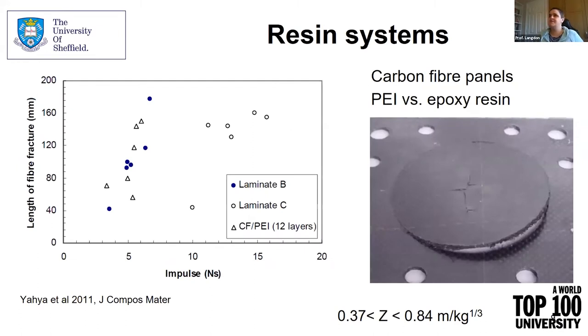So now, instead of the carbon fiber PEI panels that we saw in the last slide, we're now going to compare them to carbon fiber epoxy systems of equivalent mass. If you have a look at the graph on your screen, which shows the lengths of the fractures that we saw in the material compared against the impulses applied, where impulses are roughly equivalent to charge mass size, you can see that there's no particular influence of the polymer matrix on the failure and response. So this illustrates for us the dominance of the fibre over the resin in blast response. And in fibre systems such as glass and carbon, this is very typical.